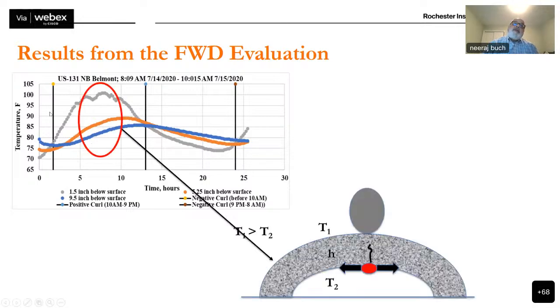If you look at this part here, the slab was positively curled because the surface, the gray line, was hotter than the blue line, and the orange line was somewhere in between. So in reality, when we measured the temperature, there was actual positive curl in the concrete pavement, just like the theoretical picture I showed you.